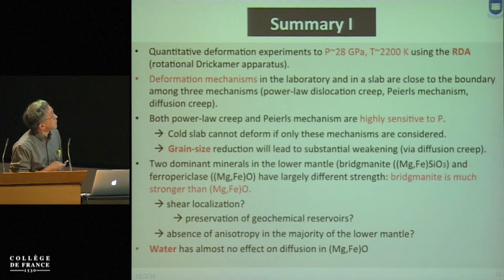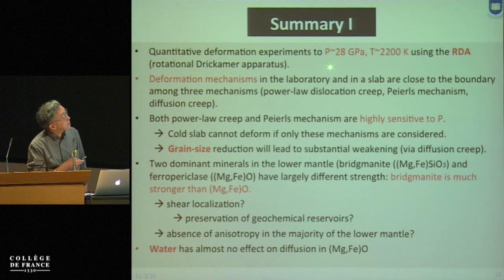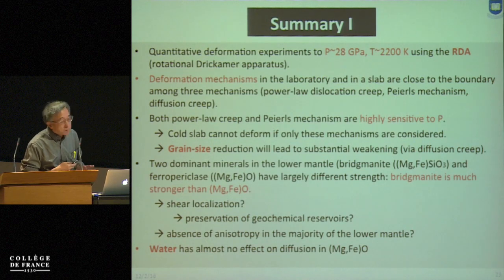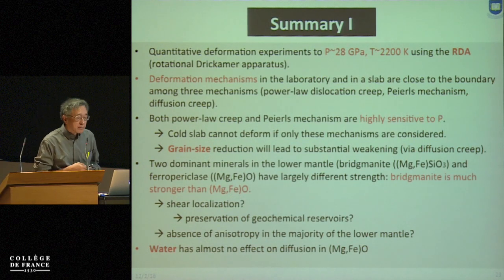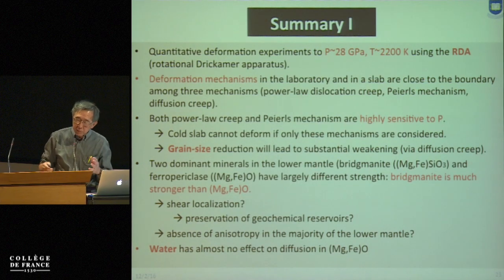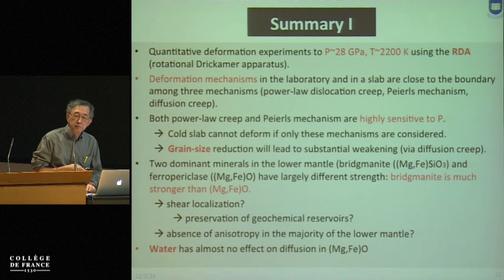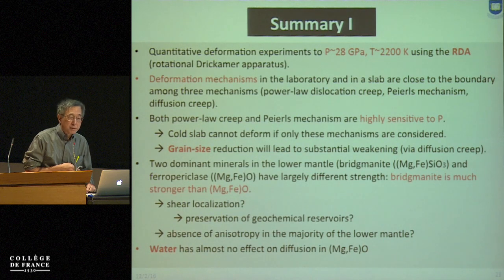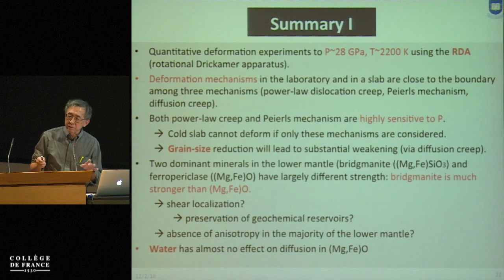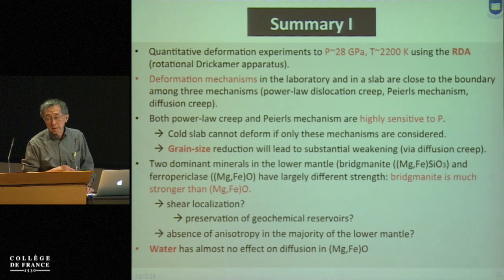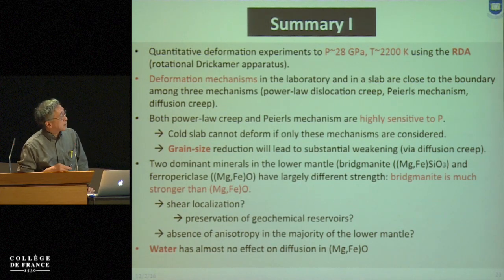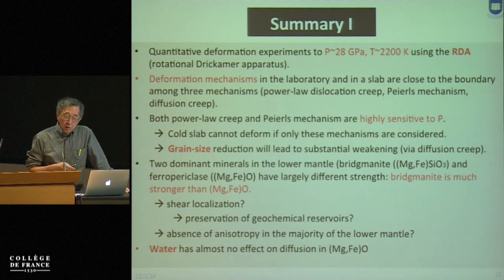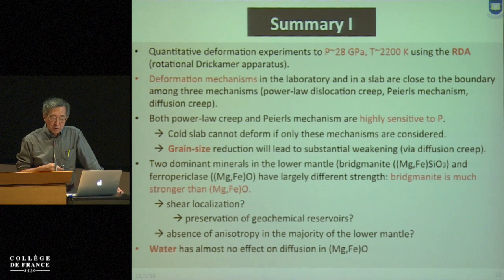So to summarize, quantitative deformation experiments have been done up to 27.8 GPa. The first results on lower mantle deformation were obtained. In the transition zone, deformation experiments were conducted over a pretty wide range of conditions, showing that deformation conditions in the laboratory are very close to the boundary between diffusion and dislocation creep. Then if you extrapolate using semi-quantitative results, you can also speculate that grain size reduction plays a very important role, particularly under lower temperature conditions. And in terms of water, available experimental results and other observations, in my opinion, strongly suggest that the water weakening effect does not occur in the lower mantle. This has a potentially very important implication for water circulation.